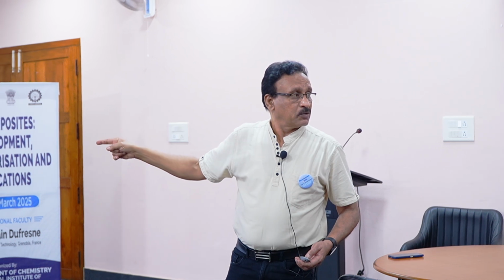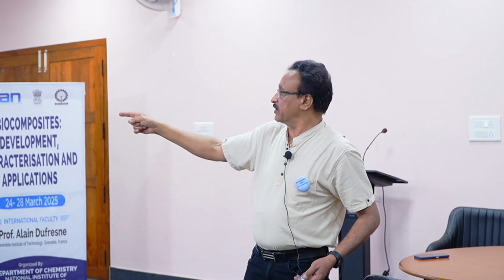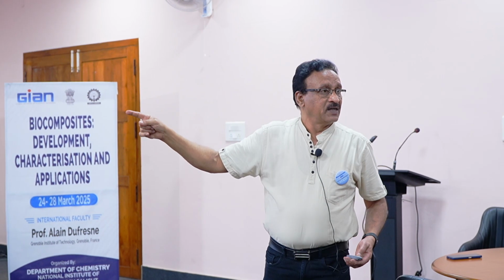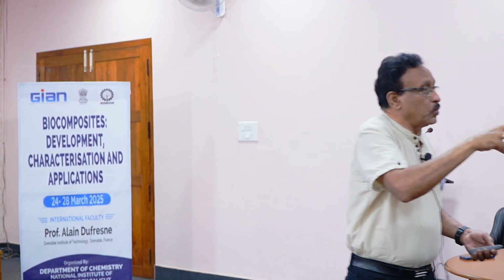So we can see that there are 4 systems: one without silver, and the other 3 systems with silver. You can see that the blue is the top one. Silver anchoring onto the PLA is another evidence. PLA alone has very low strength, the green graph. But the modulus of the system goes significantly up, almost 2 times, 2.5 times, because the silver is getting anchored.